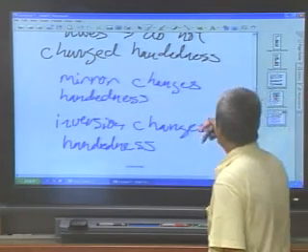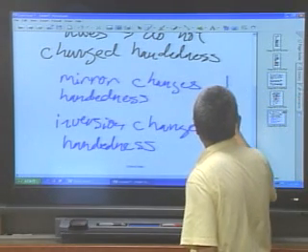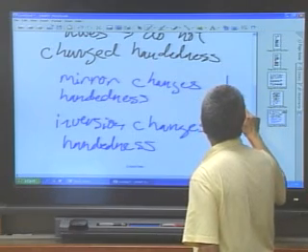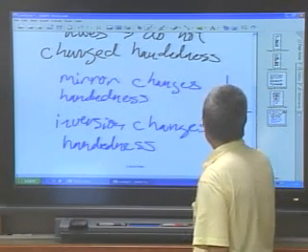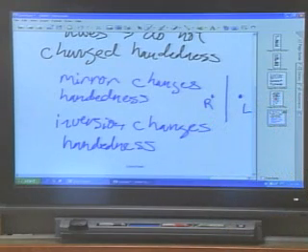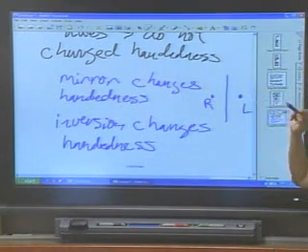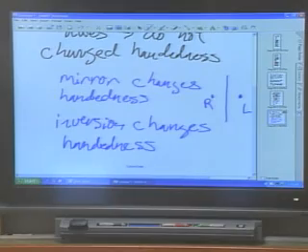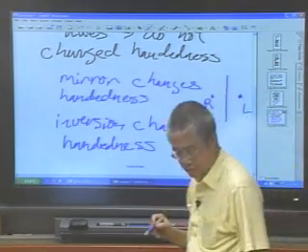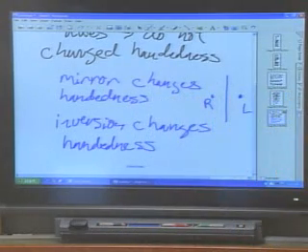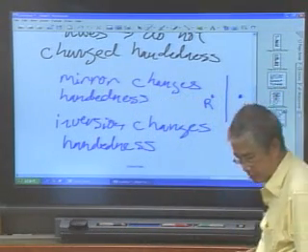Now, a mirror doesn't pose a problem by itself, because if you have a mirror plane and a point here, and suppose this is a right-handed point, when you go to the other side, this will be a left-handed point. When you come back, it'll be right-handed. So that's equivalent. But when you do combinations of rotation and mirrors and so forth, you have to make sure that if you start off with a right-handed point, when you come back to that point, it should still be right-handed. So the equivalency is not only in terms of position; it also needs to be equivalent in terms of handedness.